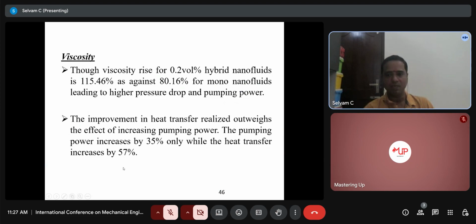At the same time, we are getting the heat transfer enhancement up to 57%. So there won't be a big issue with increasing the heat transfer rate by increasing the pumping power. But pumping power also should not be increased too much; that we should take care of. So in our case, we don't have any issue with respect to the pumping power, and we don't have any issue in the heat transfer.